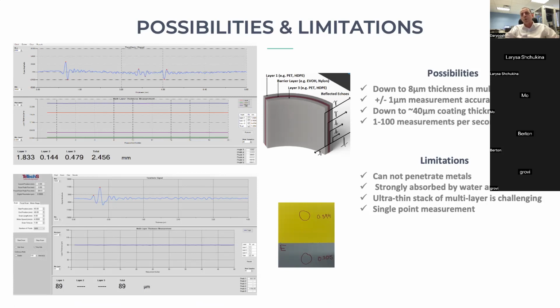When an ultra thin stack of multi-layers are stacked on top of each other, and they're very thin layers, that also makes it challenging because the echoes start to overlap too much, and peeling them off becomes a challenging task from a signal processing perspective. And it's a single point measurement in its nature. You measure 1 point at a time with this technique.